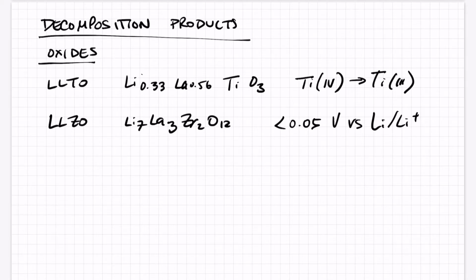So the SEI that forms, that chemical potential difference, is not going to be quite as much. So in the reduced form, the species that you can expect could be Li2O, right? That's not a highly ionic conducting compound. Lanthanum, and also if you go low enough, potentially zirconium metal. Now that is rare, but it is possible.